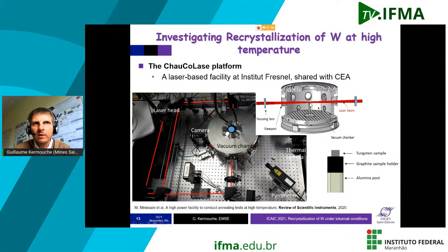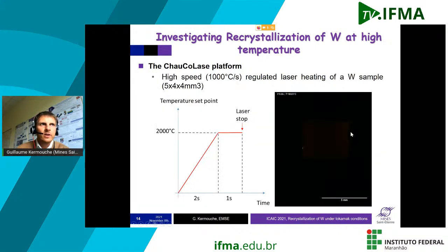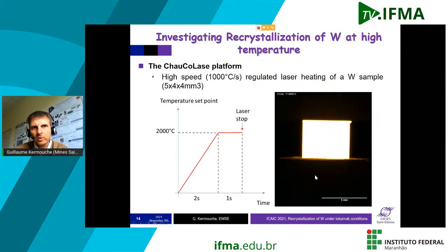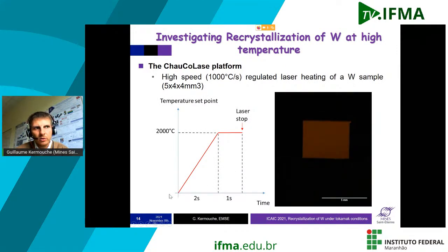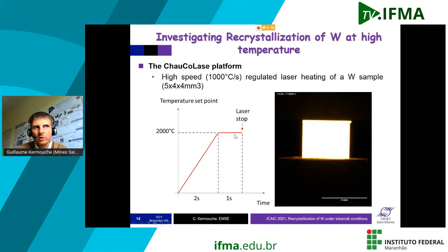This sample is irradiated on both sides, and the temperature rises up to a very high temperature, here 2000 degrees. Here you can see what happened on the sample. This is a real-time experiment. The temperature reached 2000 degrees in less than 2 seconds. So we have a heating rate that can go up to 1000 degrees per second, and then we can stabilize and regulate the temperature.